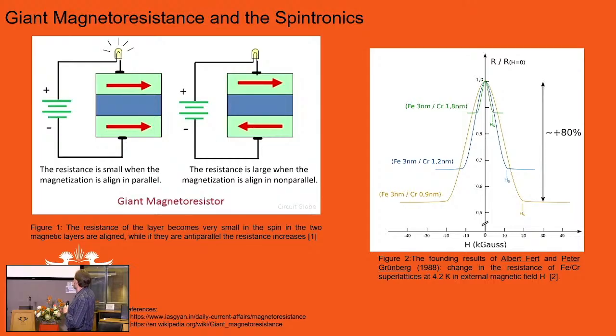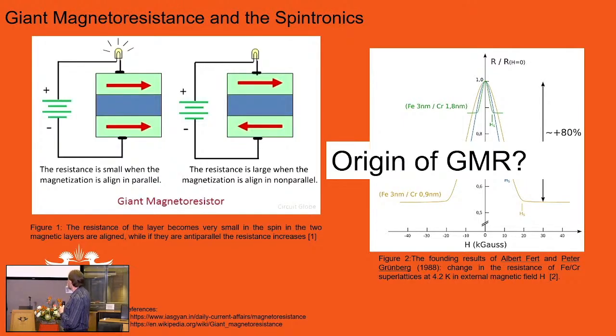If you then apply a small field on a free layer, say for example this free layer, that little magnet flips in the iron. What then happens is you now have current flow. That's a low resistive case. The nice thing about it is that the difference here is plus 80%. Effectively, you have a switch, and it's very sensitive to small fields in this case. Okay, now the question is, where's GMR? I just told you about little magnets, antiferromagnetism and ferromagnetism in this case. Where does this all originate?